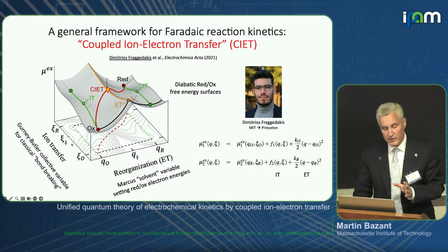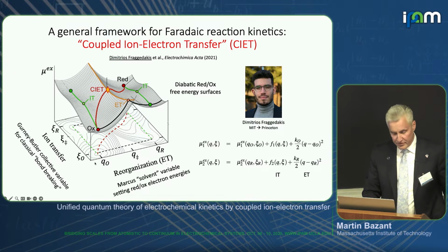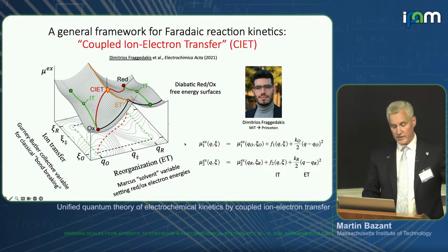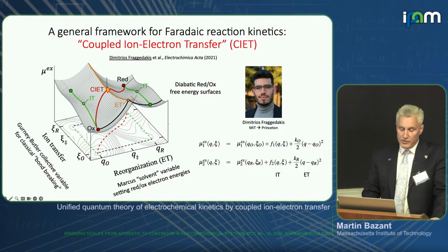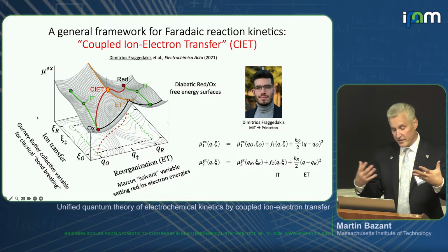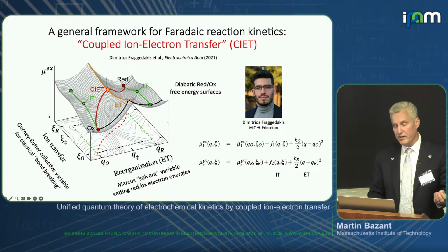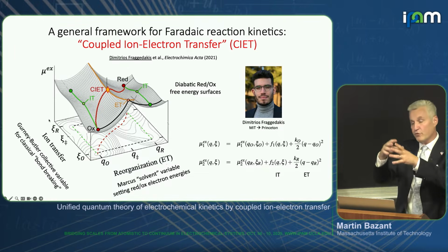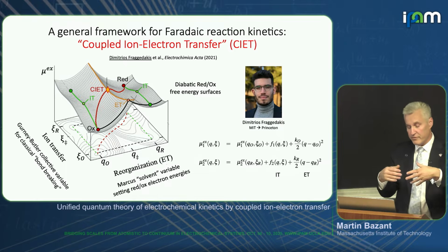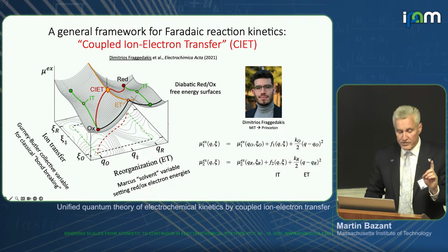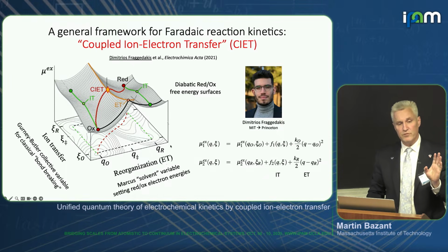And so the picture that we developed here, coming right from PCET theory, is that we have this Marcus reorganization coordinate that I talked about before that really controls electron transfer, but there's also a collective variable in this direction. I'm now giving credit to Gurney and Butler for first formulating that way of thinking: that the position of an ion, in this case think of the lithium ion being inserted, or some collective variable associated with the movement of an ion, like for example breaking a bond in some molecule, is that this coordinate we treat classically, and this coordinate is more quantum mechanical.